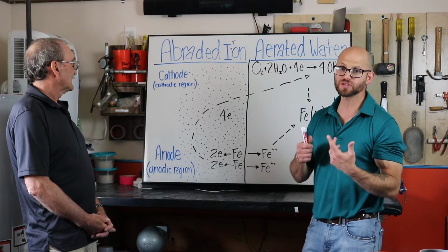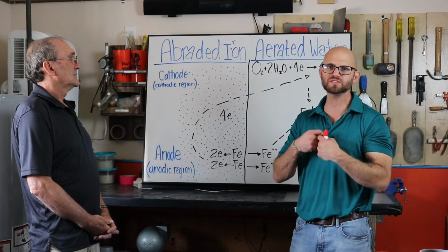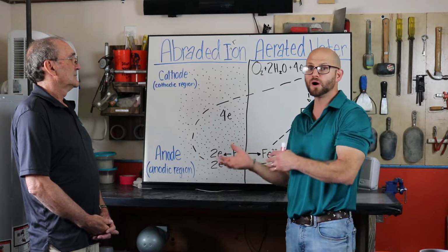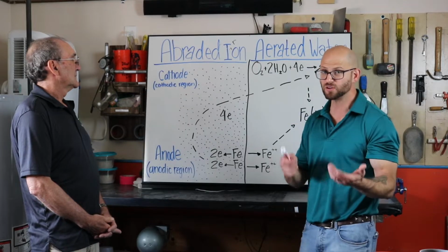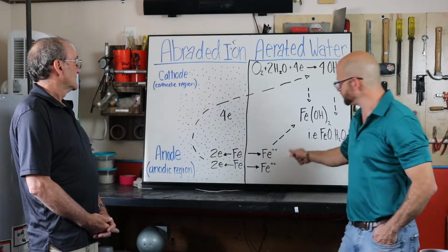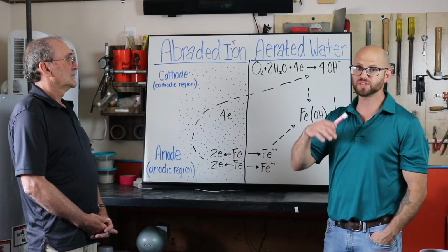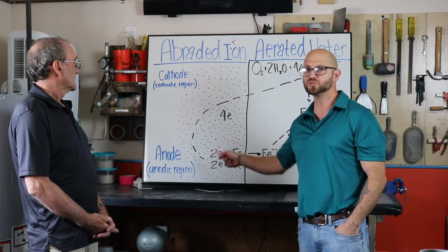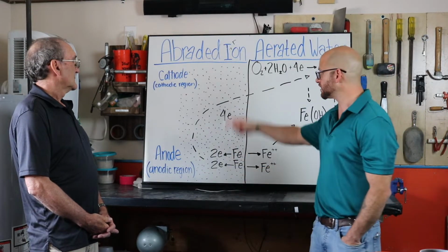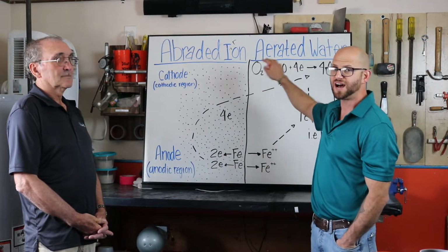What that means is, on the surface of our reinforcing steel, we do have some free atoms that are ready to give up some electrons, as well as pop off that surface, especially if you have something like water and oxygen to accelerate that reaction. That's ultimately what we see when we put our steel in our salt water bath. Right at the surface, we're going to have that release, that disassociation of iron off of our steel with the positive 2 charge. We still have 2 electrons within our anodic region that are going to contribute in our cathodic region to the development of hydroxides with those electrons, oxygen and water.